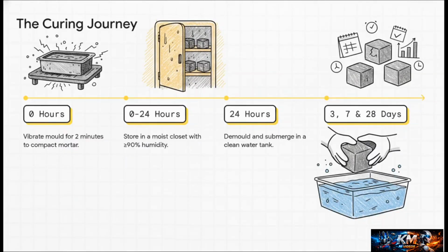And it's not as simple as just filling the mold. First, it goes on a vibration table for 2 minutes flat. This gets all the air bubbles out. Then, it spends its first 24 hours in a really humid room. We're talking 90% humidity or more. After a day, we take it out of the mold and sink it in a tank of clean water. That's where it'll live while it cures and gets strong. We'll test samples at 3 days, 7 days, and the big one at 28 days.